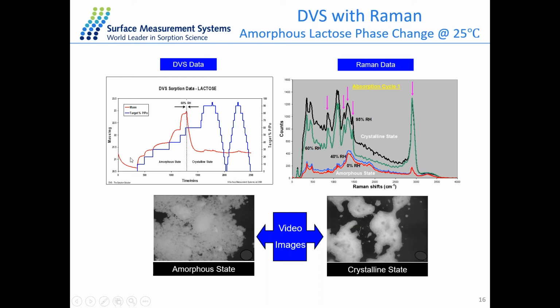At each stage, the sample is picking up moisture, reaching equilibrium, and then jumping to the next stage automatically. But as you can see at 60% RH here, there is a significant decrease in the mass of the sample. This is due to the amorphous to crystalline phase change, because the crystalline state material has smaller surface area as well as less sorption capacity. This kind of amorphous to crystalline phase change is irreversible, as you cannot see the same effect in the second cycle here. So that's something we can get from our DVS data.